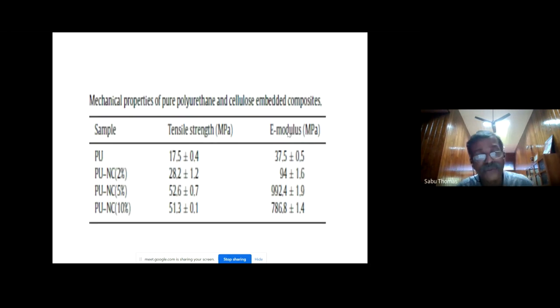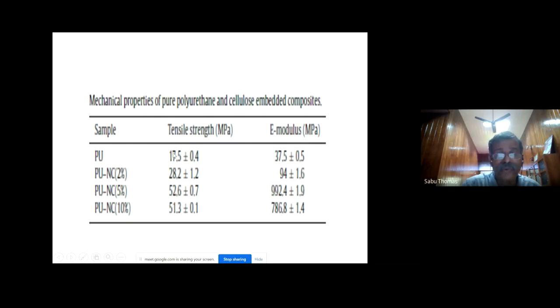Let me show you another interesting work. We have been working with Brazil for many years. My Brazilian collaborator is very active in making polyurethane, medical grade polyurethane. And if you look at the mechanical properties of medical grade polyurethane, it is 17.5, modulus is 37.5. And what we did is, we introduced 5% of nanocellulose made from pineapple leaf. You look, the modulus becomes 992.4. 37.5 became 992.4, a quantum jump.